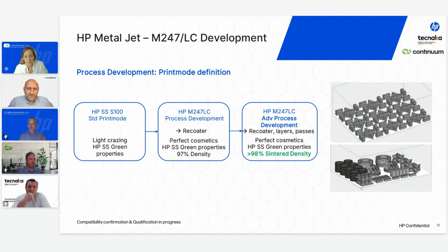As I said, we started with the standard print mode, S100 for stainless steel. And with this powder, we predicted that we were going to have some kind of slight cosmetic issues to start because this powder was a bit coarser than what we used to work with before. But we needed that, right, to have a starting point and to start prioritizing all of our properties, converging into the full combination of all of them.